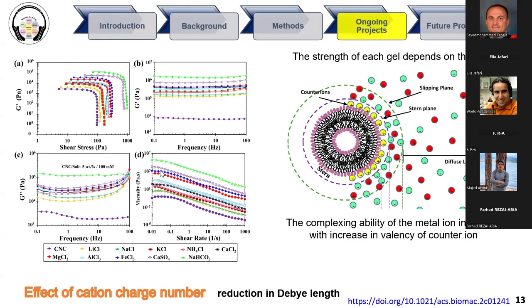The first reason is reducing the Debye length. Whenever we increase the cation charge number, we increase the ionic strength. For example, imagine we have two particles of cellulose, and there is a salt between them, and this salt acts like a bridge. Whenever we increase the strength of this bridge, it can reduce the distance between these particles, I mean the diffusion layer, making these two particles closer to each other and forming a network between them, entanglement between these fibrils, and increasing the concentration. So this is the reason why cation charge number is so important for us.